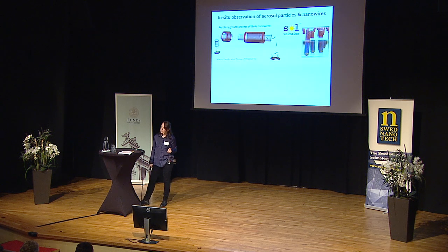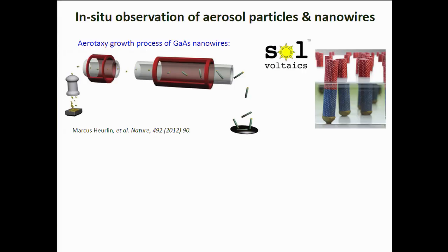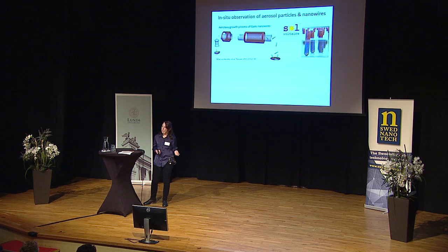So these techniques are being used for a rather new experiment at the NMC, which is in situ characterization of aerotaxy nanowires. You heard a little bit about aerotaxy earlier, but just to remind you, they're nanowires grown in a flow reactor without the use of a supporting substrate at all. So these have huge potential for reducing the cost and improving efficiencies of nanostructured solar cells. So in this way, it provides us this really unique system to observe the nanowires during the growth process with X-ray diffraction and observe the change from the particles where you have your starting gold catalytic particles all the way to the gallium arsenide nanowire growth.